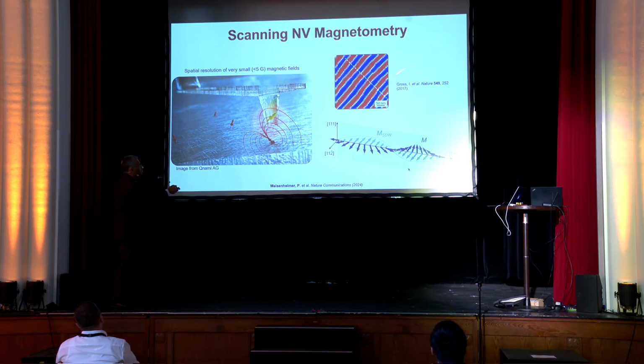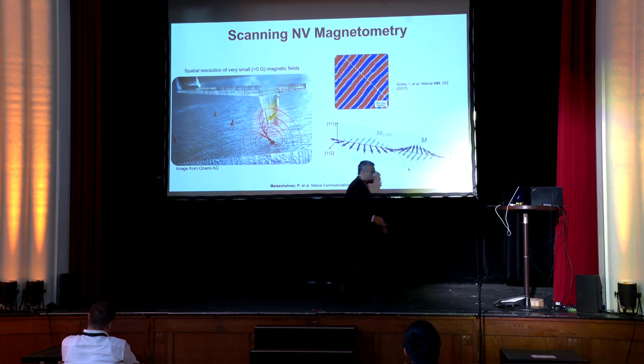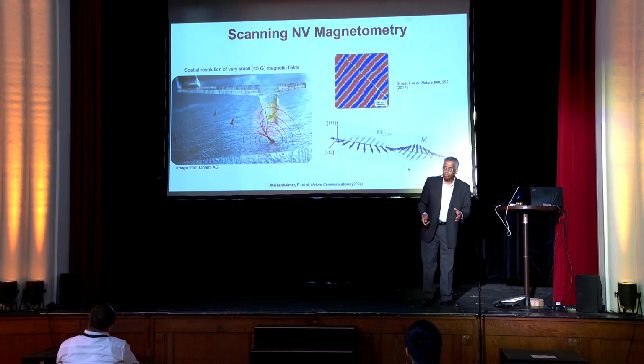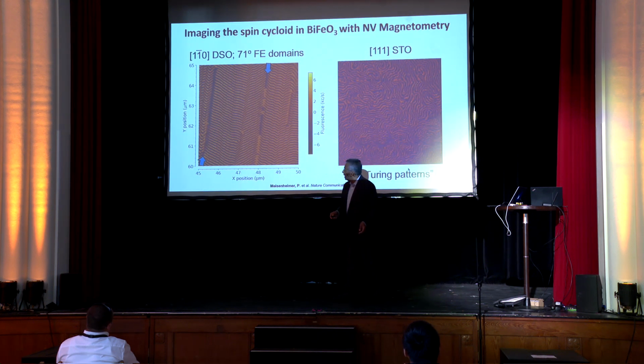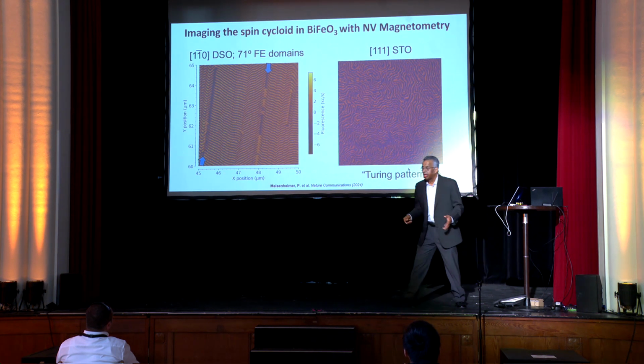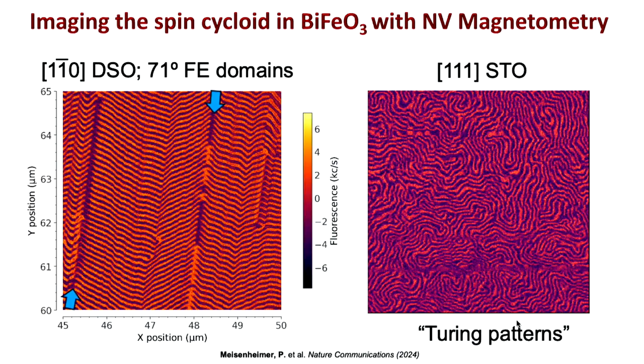So this paper is a beautiful paper from the folks at Thales, where they imaged the spin cycloid. This is the cycloid itself. The spacing is about 65 nanometers using the NV system. That's the cycloid that they were imaging. And it turns out that it's so good, we started collaborating with people. And it became so exciting that we said, we need to go buy one of these. And indeed, we do have one of those in our lab. It's a very specific piece of instrument. It's very sensitive, but you can get some amazing, amazing images.